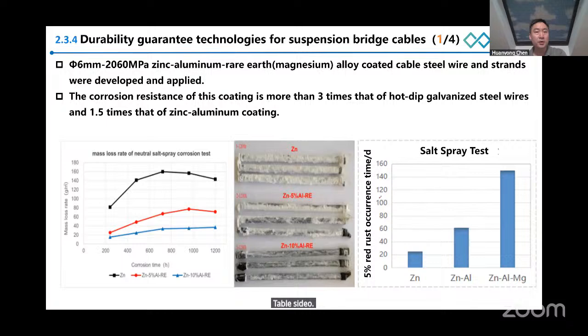Number 4, durability guarantee technologies for suspension bridge cables. Phi 6 mm, 2060 megapascal zinc aluminum rare earth magnesium alloyed coated cable steel wire and strands were developed and applied. The corrosion resistance of this coating is more than 3 times of hot dip galvanized steel wires and 1.5 times that of the zinc aluminum coating.